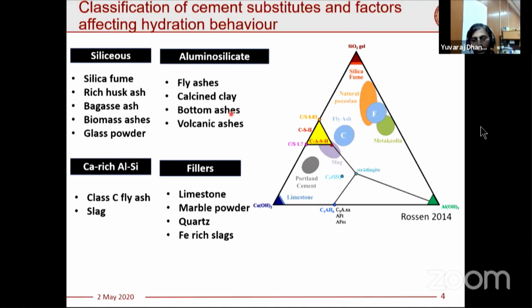Then you have other classes of SCMs where the reactive part of the SCMs contains aluminosilicate component in the amorphous content. So you have fly ashes which have reactive alumina and silica. You have calcined clay, bottom ashes, even volcanic ashes have certain amount of alumina in it. Then you have the other categories of SCMs which are calcium rich glasses. So you have calcium along with alumina and silica in the reactive component. So these will come right up here in the ternary chart. So because these have calcium, it's not going to as effectively consume calcium hydroxide as such.